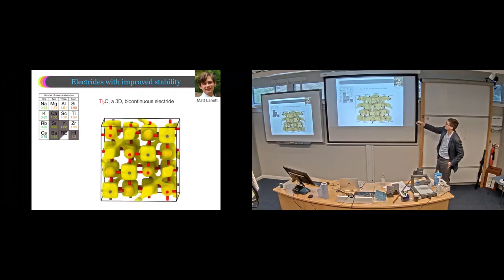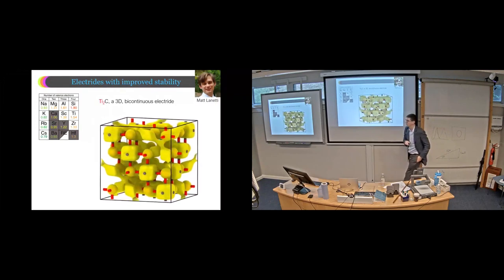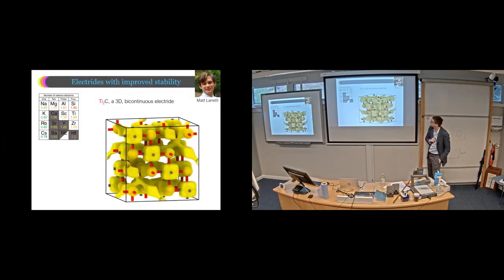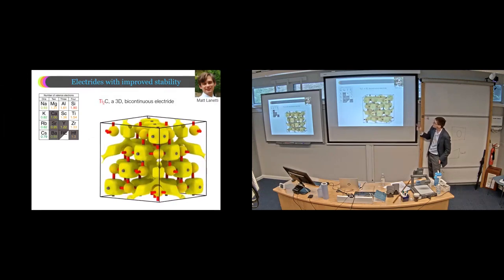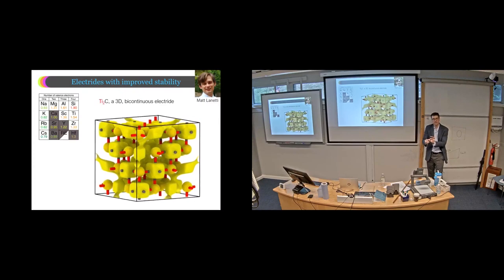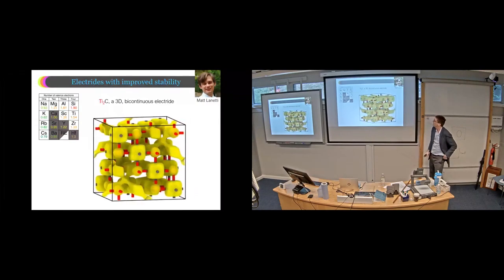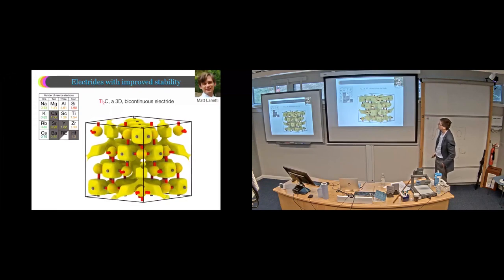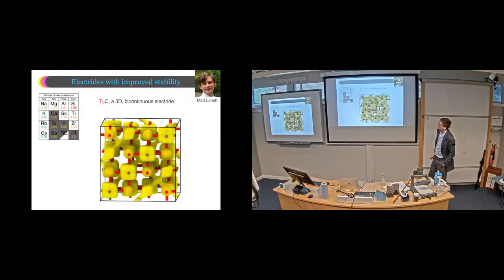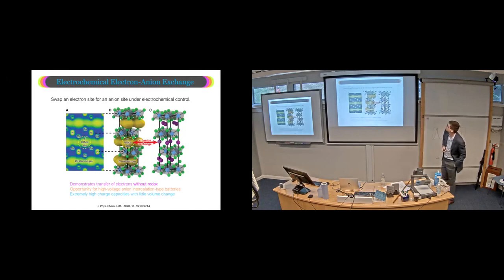So Matt has synthesized this material and it's really quite interesting. So you can see this diamond-like network of this electron gas. It has these octahedral sites that are connected via tetrahedral so that it has tetrahedral nodes just like silicon or diamond. The atoms themselves also form a diamond structure. So you have two interpenetrating diamond structures, one of the electron gas, one of the atoms themselves. So this is what you would call, at least in the block copolymer morphology literature, you would call this a double diamond structure, two interpenetrating diamonds. And they are fully continuous. So it gives us a pathway for intercalating fluoride into this system. This, I believe, is the first 3D electride. That is, the topology is this 3D connected network. So we are wrapping up that and we'll have that paper submitted shortly. But this is quite, I think, an exciting path forward for us.